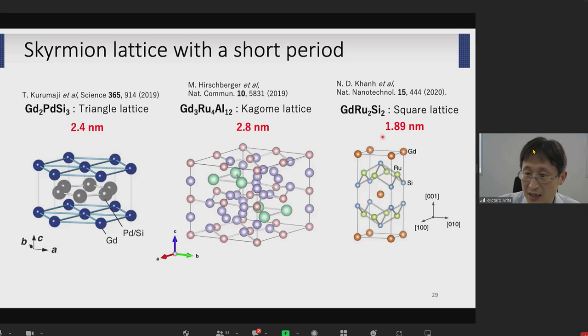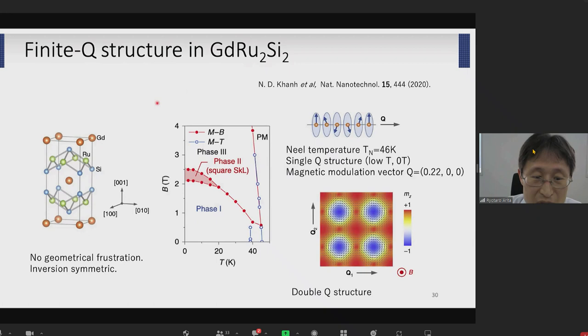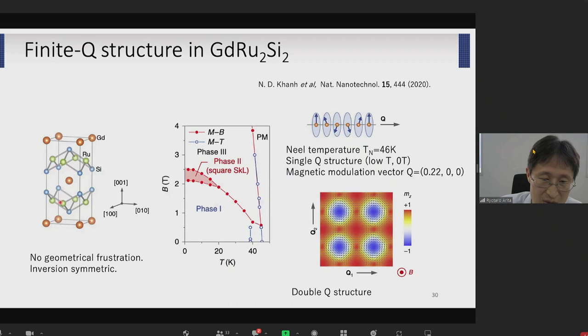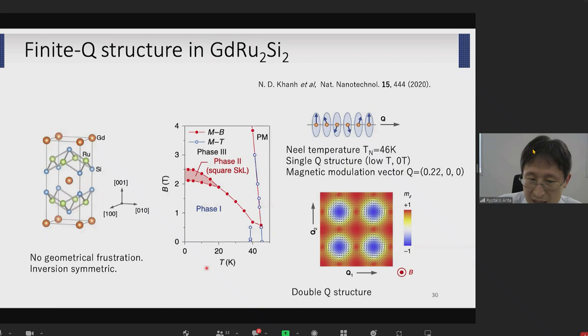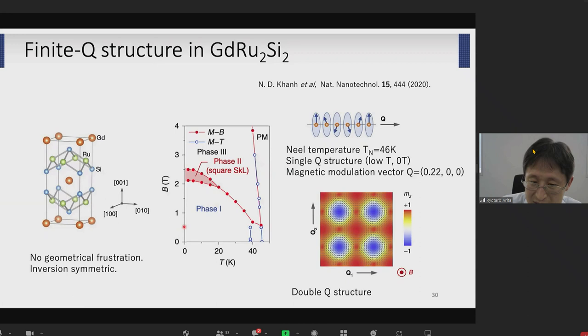Gadolinium-based compounds — such as Gd2PdSi3 or Gd3Ru4Al12 — show skyrmion phases. They consist of triangular lattice, Kagome lattice, or square lattice. The size of the skyrmion is very small: 2.4 nanometers, 2.8 nanometers, or 1.8 nanometers — more than 10 times smaller than skyrmions in non-centrosymmetric systems. For example, in the case of GdRu2Si2, this is the crystal structure — it's the same as the 122-type iron-based superconductors. The system has no frustration: ruthenium and gadolinium make a square lattice, and the system has inversion symmetry.